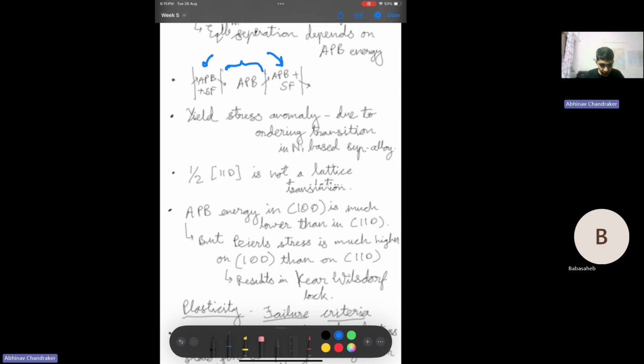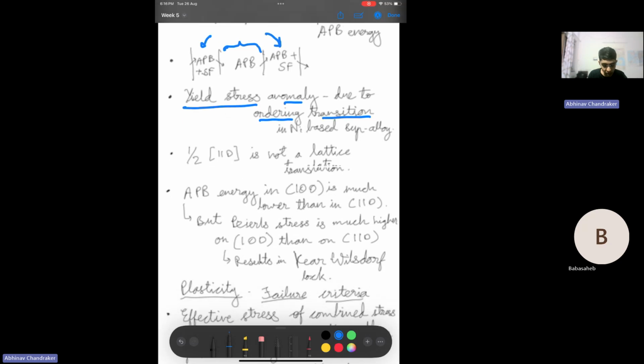And because antiphase boundary is forming, which is associated with higher energy, the general observation is that this leads to an increase in the strength, because the movement of dislocations in the ordered phase is more difficult since APBs are forming, compared to that in a random lattice which has no ordering, which can be called a matrix phase. So because of this ordering and APB generation, the dislocation motion is difficult, and as a result the strength is higher. So in case we have an ordering transition in any alloy such as nickel based superalloy, that will be associated with an increase in the yield stress, and this phenomenon is also called yield stress anomaly for Ni based superalloys.